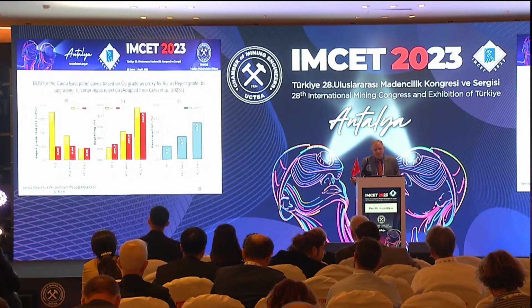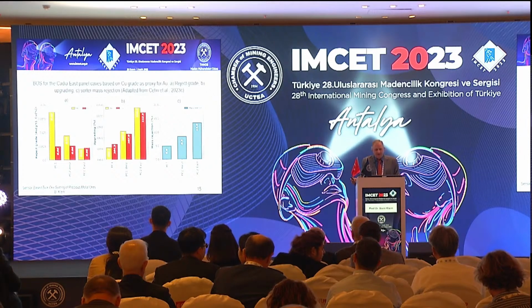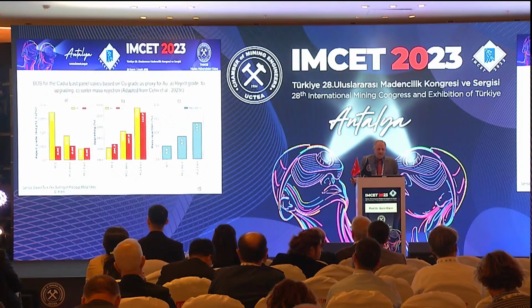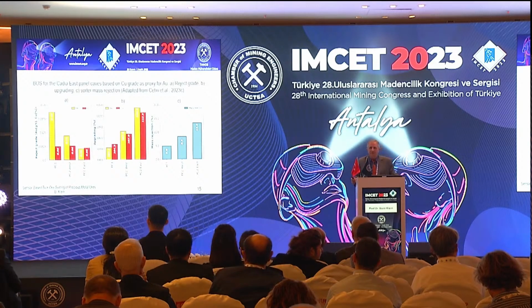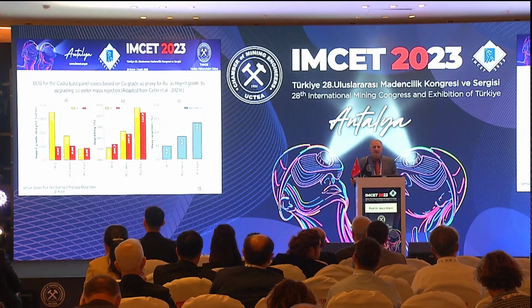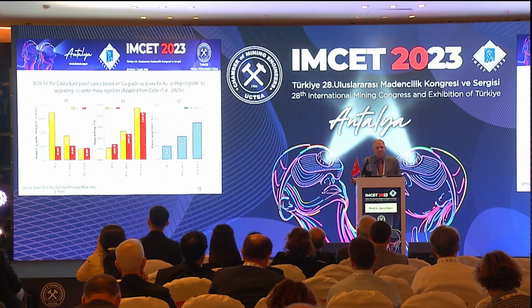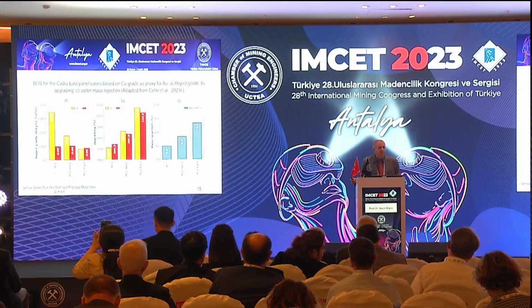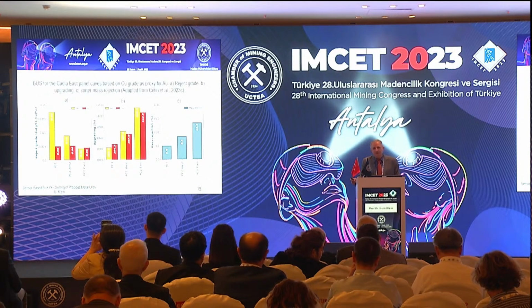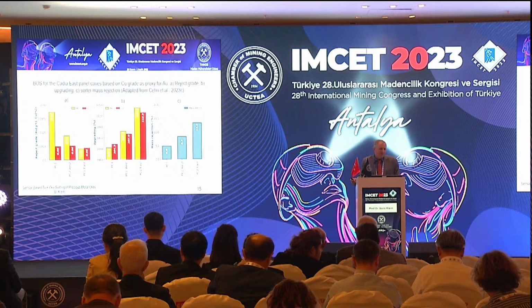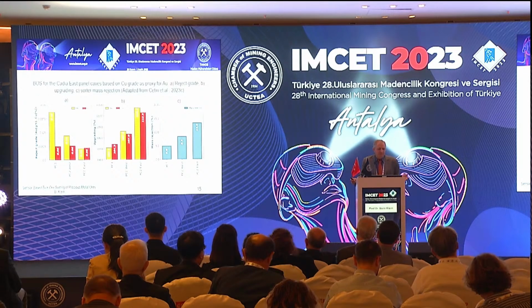This was an example that was conducted for the Cadia East panel cave mine, and without going into too much detail, the issue here was that they contained both chalcopyrite and bornite, and at depth there were varying ratios of gold to copper. It wasn't constant. As well, it's a fairly heterogeneous deposit. So if we sorted based on copper, we were able to get quite low reject grades of copper, but not so effective for gold.